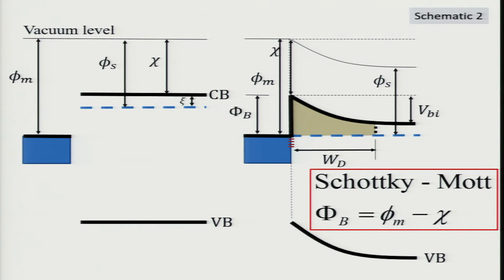relationship, the Schottky-Mott relationship, except for the fact that sometimes there can be surface states where the Fermi energy gets pinned to the surface states, and there's a high density of states there, and the Schottky-Mott relationship has to be modified by these high density of states where the Fermi energy gets pinned here. In some sense, if you have a high density of surface states, the semiconductor doesn't recognize the work function of the metal. Okay.